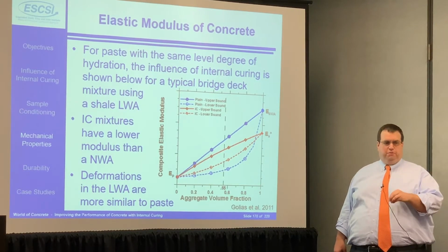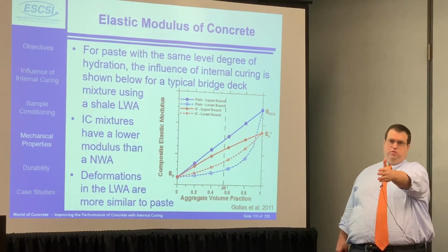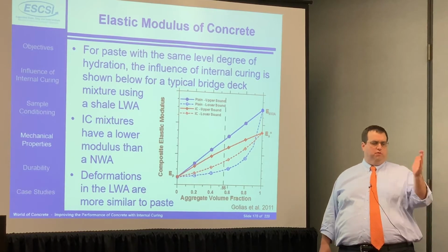With rare exceptions, the high rise where you're worried about getting a high elastic modulus to provide stiffness, lower modulus is better. So when we're talking about flooring slabs, when we're talking about bridge decks, the lower modulus makes your concrete more extensible. It stretches easier, right? So you think about the fact that you've got stresses building up. If the modulus is lower, the concrete's a little stretchier, all right, than it would be in other cases. So having that lower modulus is not a problem.